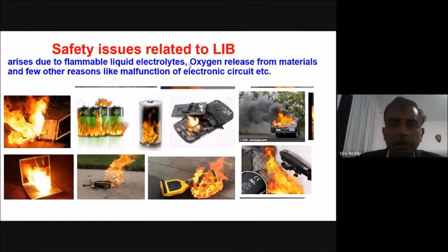Either the flammability of the electrolyte is one reason. Another is oxygen release from the materials. Sometimes people may exceed the safety limit due to malfunction of the electronic circuit, where there is a safety breaker. Sometimes a particular system may go to a higher voltage than expected at the time. Sometimes you may see capacity degradation, or oxygen release, and due to repeated cycling, it may catch fire also.